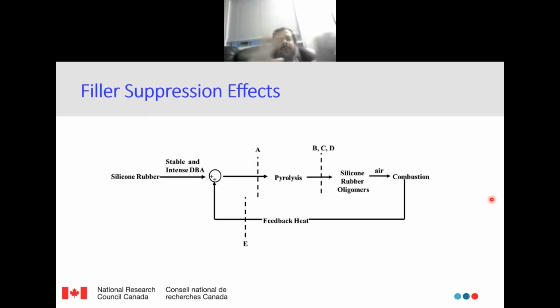This is a sort of flow diagram of what is happening on the surface of the material. We have the silicone rubber material. Now the dry band arcing will start to take place. You will have a pyrolysis effect on the surface of the material. You will have combustion because you have this dry band arcing under air. Now this will come back, and this cycle will keep going on until the material completely fails on the surface. Our objective is to develop a material that can withstand this cycle for the prescribed time, which is 7 to 10 years.